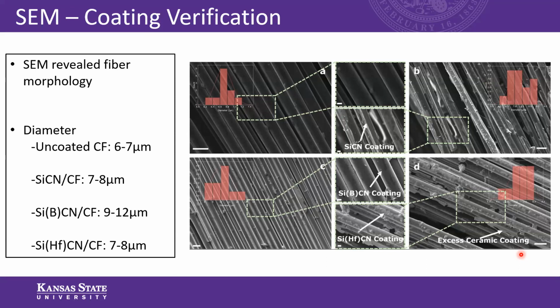One special note to bring to your attention is that for the SiHFCN sample, you can see that there's some excess ceramic coating on the sides, which is not present in something like the SiBCN sample, for example, which had a more smooth coating. And this is mainly attributed to the fact that it is likely that an excess amount of pre-ceramic polymer was infiltrated into the sample.